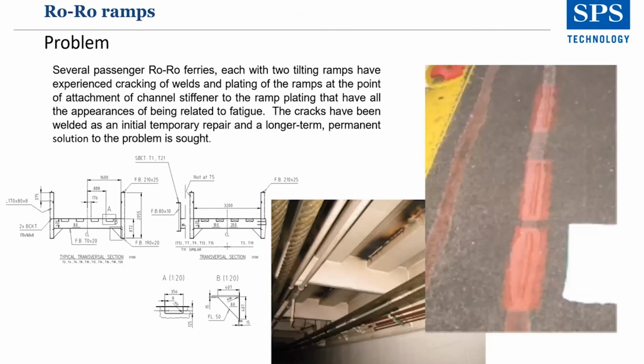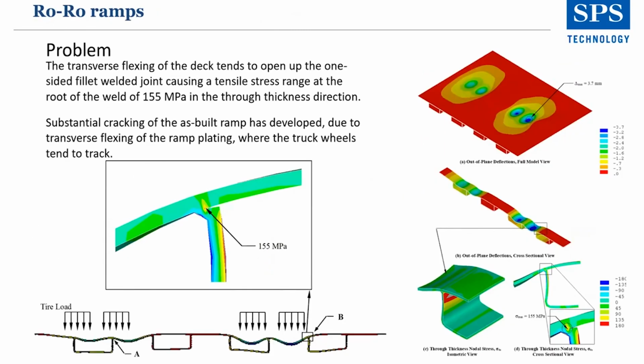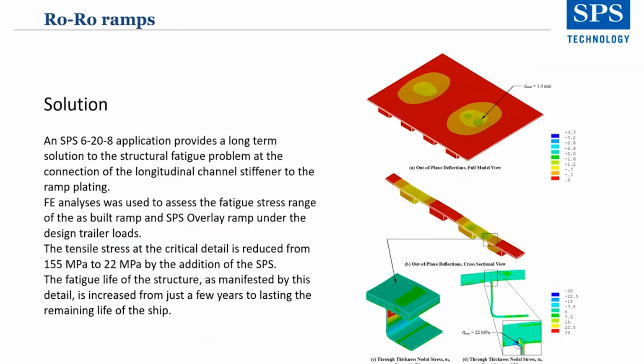For ro-ro ramps, we've had several passenger ro-ro ferries with tilting ramps that experience cracking of the welds and plating at the point of attachment of the channel stiffener to the ramp plating, and it's all related to fatigue. They've been welded as an initial temporary repair, but a longer, more permanent solution was needed because it kept on cracking. The transverse flexing of the deck tends to open up the one-sided fillet welded joint, causing tensile stresses. There was substantial cracking. We did the finite element analysis and modeling, and it was due to the truck wheels where they were on the ramp. So we installed SPS with a 20mm core, which gives a long-term, permanent, class-approved solution to the structural fatigue problem.